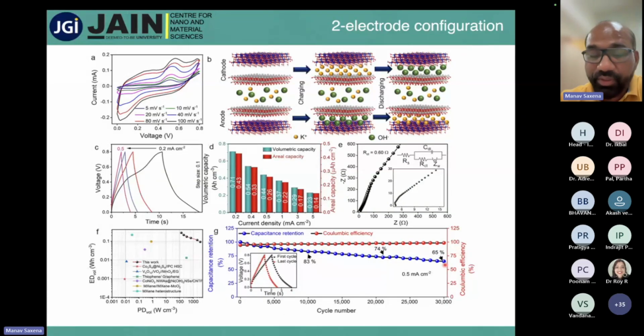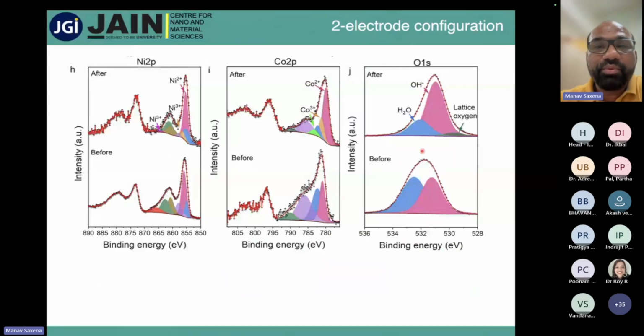65% of the retention. So what happened after charge and discharge of 30,000 cycles? Is there any change? Because performance is decreasing. Definitely there are some changes in the oxidation state of the nickel or the cobalt. So we have done the XPS before and after.